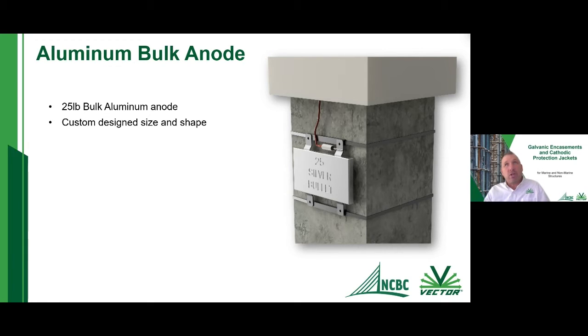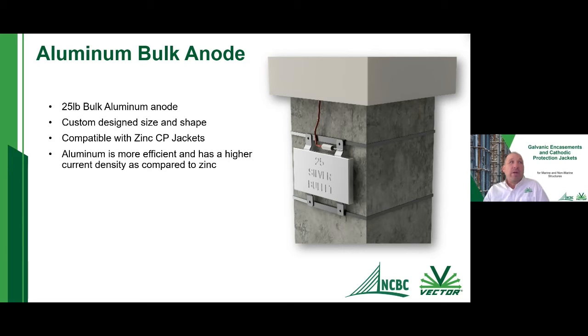One of the worries was whether aluminum would be compatible with all of these zinc jacket systems out there. From all of the tests and field trials that have been done, the aluminum bulk anode is actually compatible with these systems as well. Another thing is that aluminum is more efficient. When you have a bulk anode exposed to seawater, aluminum is much more efficient and has a higher current density compared to a zinc bulk anode. So we can use a smaller, lighter aluminum anode that's easier to install, and you get more cathodic protection current out of it and a higher current density as well. And for those instances where zinc is an environmental concern, aluminum is a much better option.